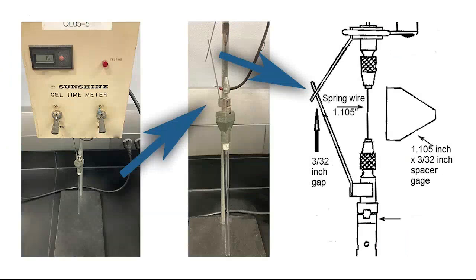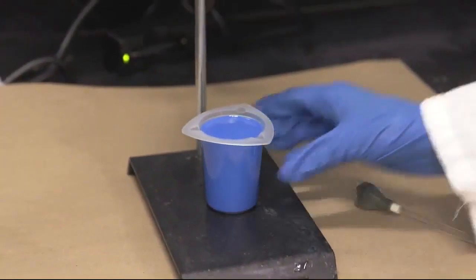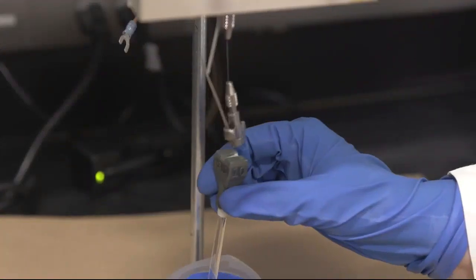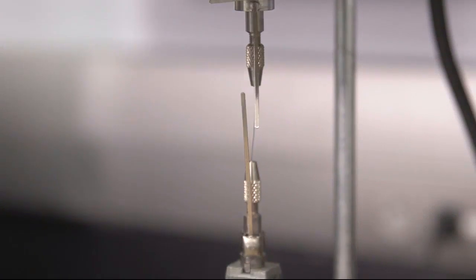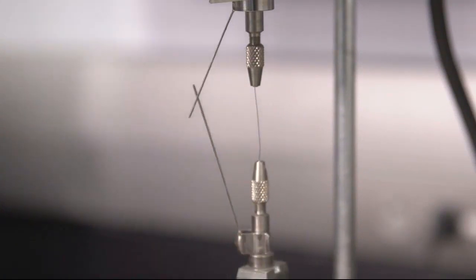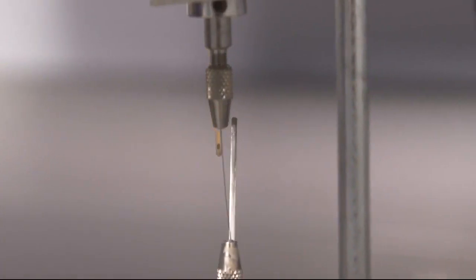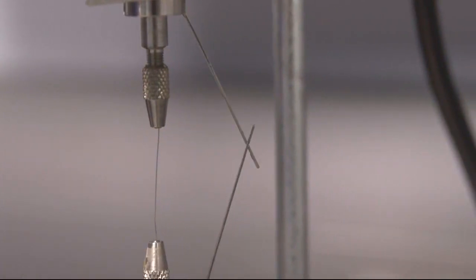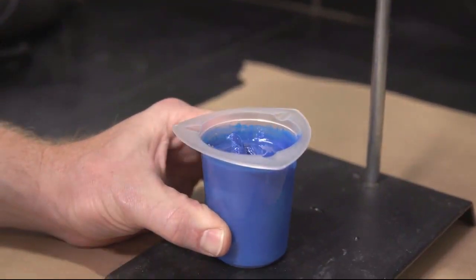Different test methods are used to quantify gel time based primarily on the speed that your application needs. The first test is ASTM D3056, also known as the Sunshine Gel Meter test. This is a diagram of a Sunshine Gel Meter. This instrument works by submersing a glass rod into the mixed material and slowly turning the glass rod. When the material reacts to the point where the glass rod can no longer rotate, the upper electrodes touch and sound an alarm. This method is primarily used for urethane systems that react very quickly for a fast transition to an elastomer. Typically, this is for systems with a gel time of 20 minutes or less.